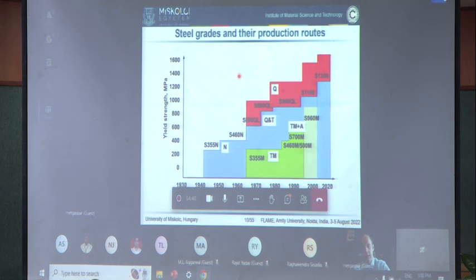Besides the automotive sector, high-strength steels are also used as structural steels. However, the types and the production processes are different. In this figure, you can see a little history of the development of high-strength steel. 50, 60, 70 years ago, the top category was the S355 strength category, where the guaranteed minimum yield strength was 355 megapascal. These steels were produced by heat treating process and rolling process. Generally, the heat treating process was normalizing.